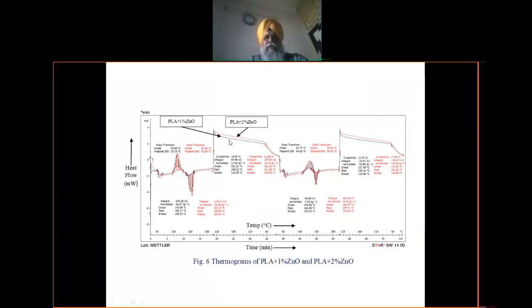Here you see this curve. This is PLA with 1% ZnO, and this red color is PLA with 2% ZnO. You see, with the reinforcement of more ZnO, the glass transition temperature was the least affected. Earlier it was 53, again it was 53.3. So there is a marginal effect on the glass transition temperature. But there is also a little effect on the energy absorbed. Like in this case, it was 21.67, and in the second case, it was 22.60.